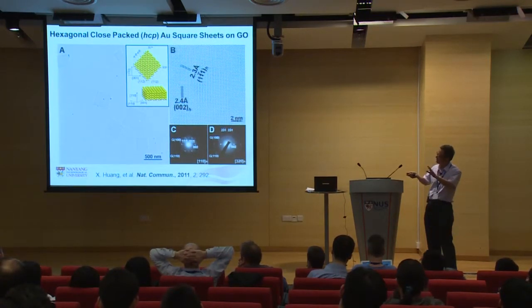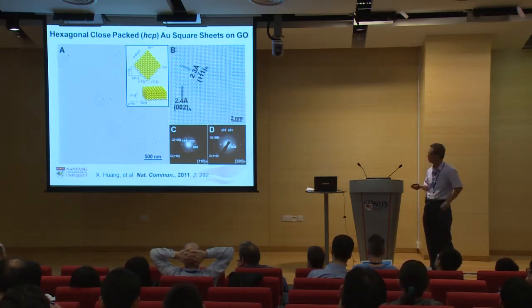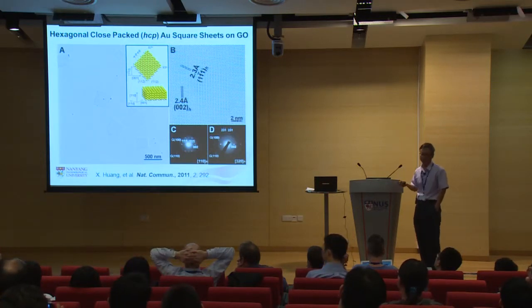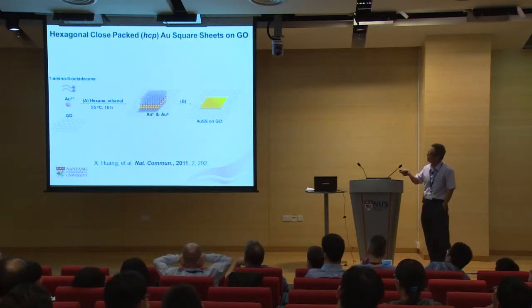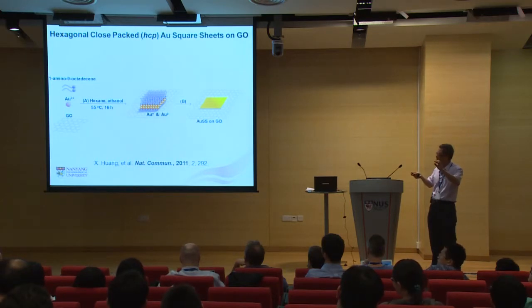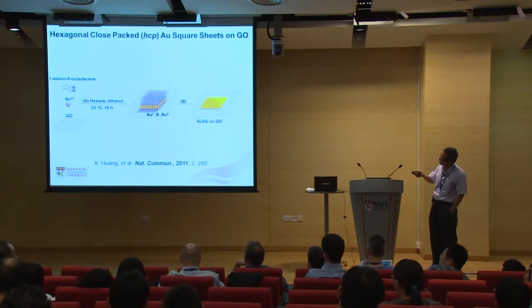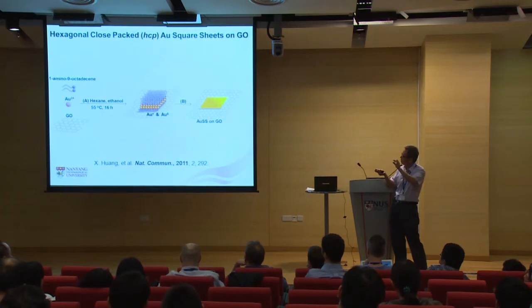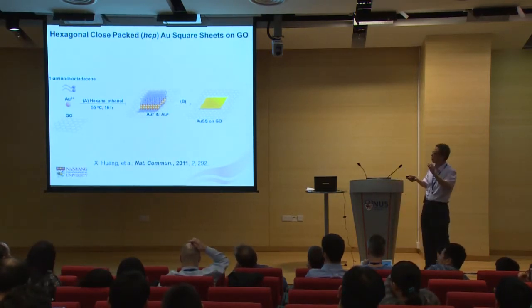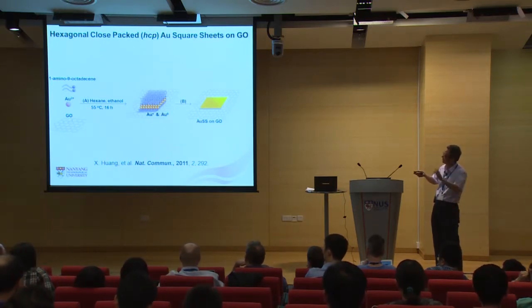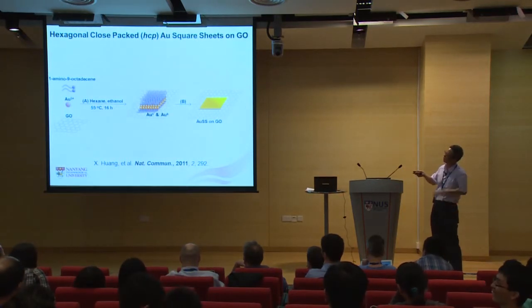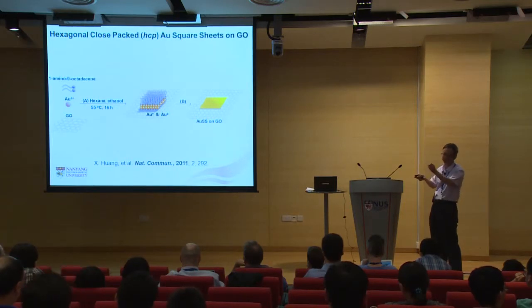The reason is that when the gold sheet is very thin, the internal energy is small compared to the surface energy, so surface energy dominates the total system energy and the HCP gold sheets are stable. As the gold sheets continue to grow thicker, the internal energy of the HCP dominates, and the HCP converts to FCC above 6 nanometers.